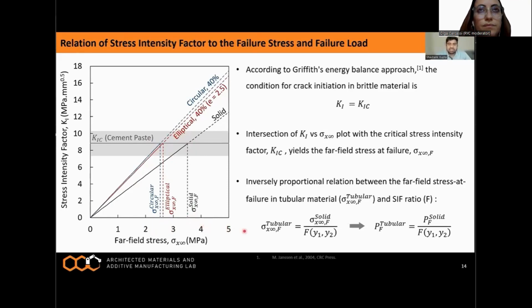Given the previously presented definition of stress intensity factor ratio, we can define the stress at failure in the tubular system as the stress at failure of the solid counterpart over the SIF ratio. In the same way, the load at failure in the tubular system can also be defined in terms of the SIF ratio. Using this SIF ratio, we can also look at the effect of the tube size and shape.